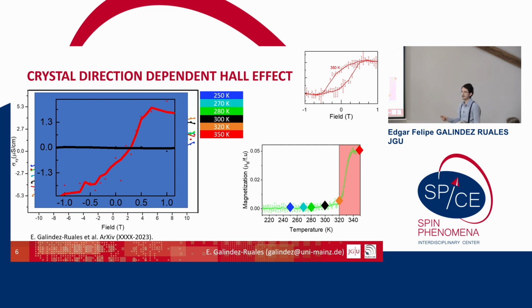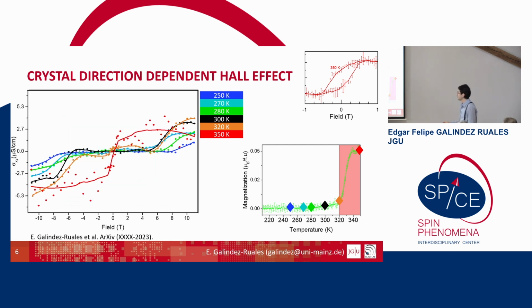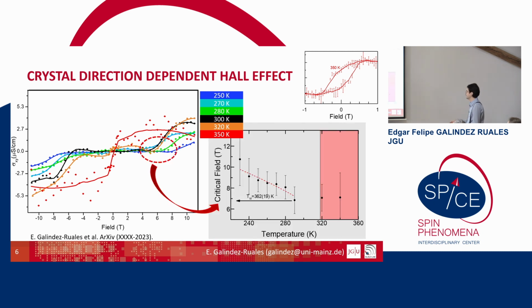So this effect we are not interested in. We are interested in the other effect that was rising. So we will have these jumps here, and then we are interested in how these jumps are behaving. We define the critical field as the maximum slope in this change, and then we plot this critical field as a function of the temperature, and this, believe me, fits into a Landau theory.